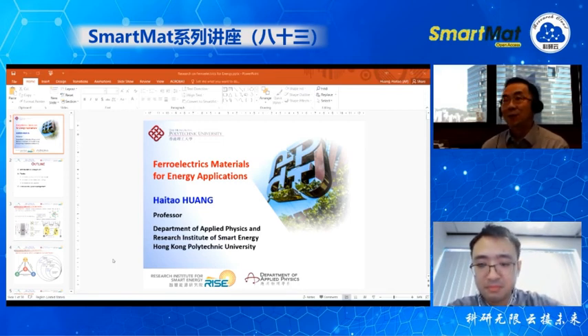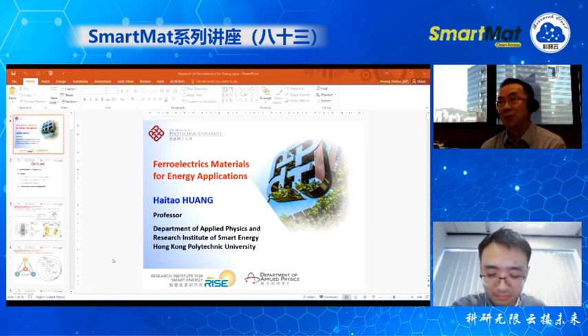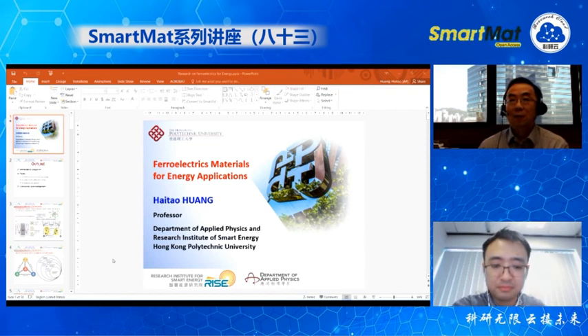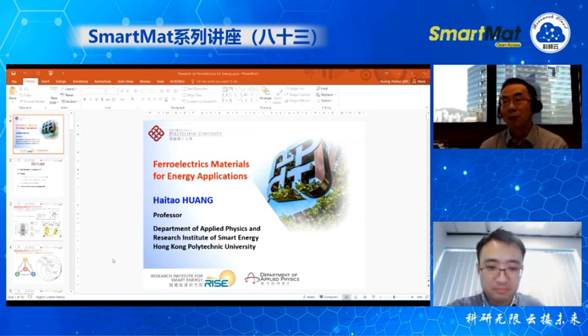And the last one, for the fabrication of the nanoparticles, is a hydrothermal method. For laboratory scale, you just buy a very small autoclave. You use an oven to heat up the material, normally up to 200 degrees Celsius, which is normally enough for hydrothermal synthesis. So for material fabrication, sol-gel and hydrothermal are very low cost, but pulsed laser deposition could be quite expensive.